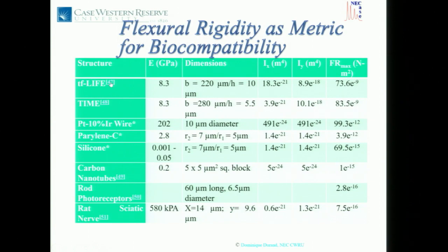So we started to look at this. Flexural rigidity is actually a well-known measure in mechanical engineering, but nobody had used it in this context. Nobody had measured flexural rigidity to determine if the interfaces that we put in nerves are similar to those of the nerve. So we measured it. Well, actually, it's not measured. This is an estimate based on the dimensions and the Young's modulus. 10 to the minus 9. The TIME electrode, 10 to the minus 9, 10 to the minus 12. This is for a platinum iridium wire, 10 micron, very thin.